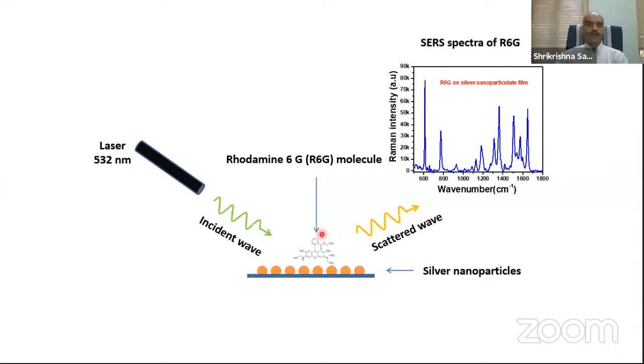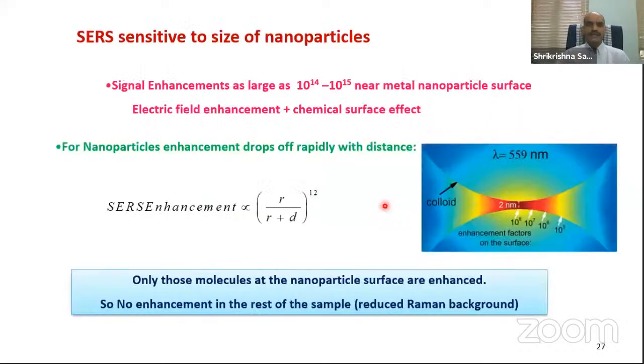So it is very useful. You can immediately see that. Otherwise, I could not detect the molecule if I put it on any surface, because there is a fluorescent background. Now this fluorescent background gets suppressed and I get a very intense Raman spectrum, and I can easily study it. I can see the intensity change with concentration and so on and so forth, so a systematic study can be done. So what I have to do is develop or coat this metal nanoparticle on a certain surface, and then I will adsorb the probe molecule, whatever probe I have.